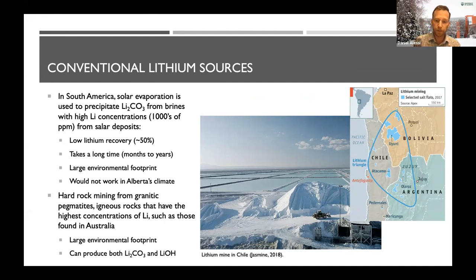In places like South America, the lithium triangle is the biggest salar producer of lithium. This is at the boundaries between Bolivia, Chile, and Argentina. You pump the brine up from fairly shallow depths and put it into evaporation ponds. So you can imagine pumping out a lot of water. It sits in an evaporation pond anywhere from many months up to approaching 2 years, and you evaporate out the water. Lithium is one of the last things to precipitate out of the water. As you evaporate water, salts start to precipitate eventually. So you can optimize this process: evaporate it, remove the stuff that you don't want, and then the water that has more concentrated lithium is moved into subsequent ponds for further purification.